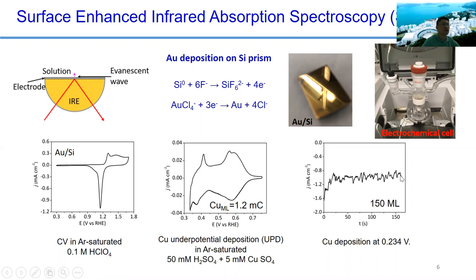So when we study the copper thin film, we first deposit a gold thin film on silicon, because if we directly deposit copper, it's very difficult. Okay. So we developed a method to deposit the gold on the silicon prism first, using hydrogen fluoride to etch the silicon surface, and the gold can be reduced on the surface. Okay, you can see the shining surface on the silicon, right? So after you make this gold thin film, you can characterize it using the chemical method. So it's a typical polycrystalline gold.